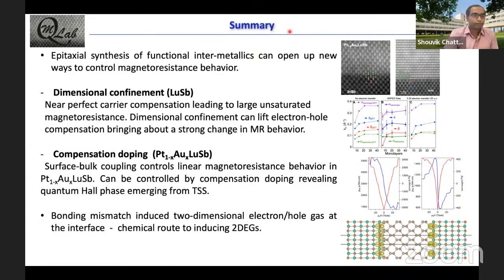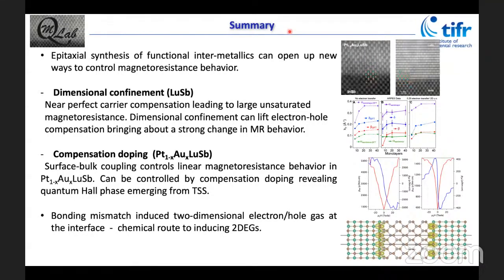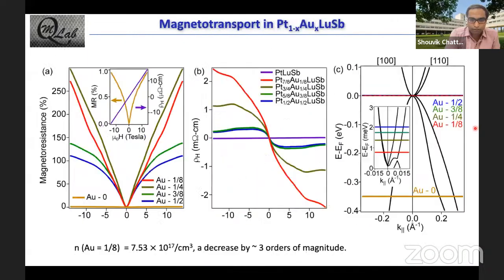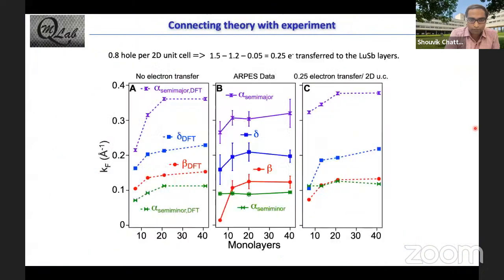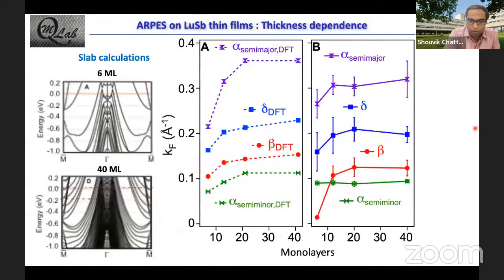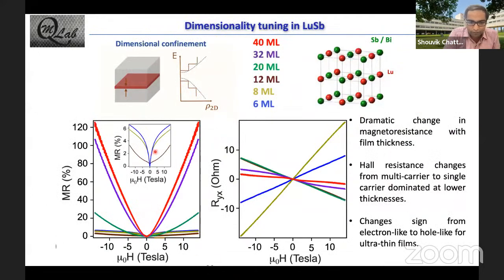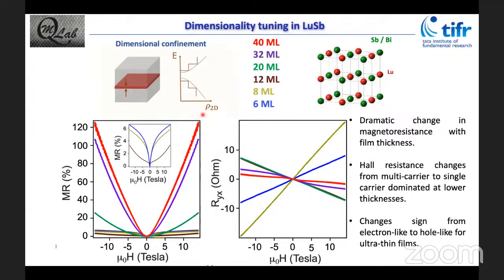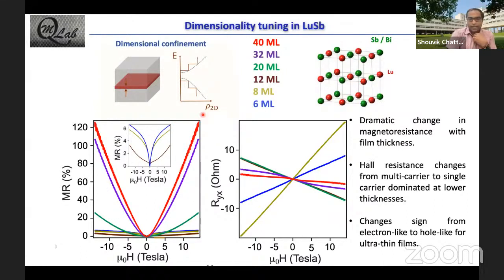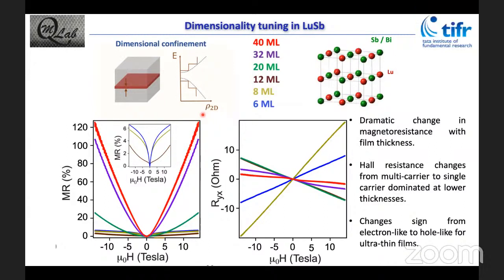Yeah, Shouvik, this is Samuel here. You mentioned that depending on the monolayer, the electron-hole compensation changes. Do you see saturation in your magnetoresistance, because your magnetoresistance was still not saturating? Yeah, we do see it in the very ultra thin limit. And I must also say that there is also influence of mobility here. So you can see that in the very ultra thin limit, it starts to saturate in 8 and 6 monolayer. Oh, I see. Okay, so your curve curves out. Yeah. And I didn't go into that detail, but the mobility also plays a role, as you would expect, in the final value that you get. Okay, thank you.